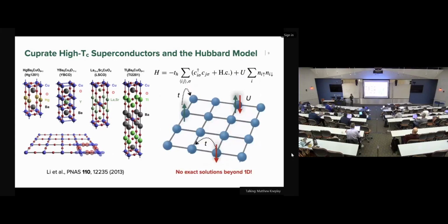The simplest model believed to capture all the key ingredients is the so-called Hubbard model, for this copper-oxygen plane. The corresponding Hamiltonian operator basically describes the energy. The first term is the hopping of electrons. For example, c_{jσ} is an electron annihilation operator, which kills an electron at lattice site j with spin σ, which can be up or down. And c†_{iσ} is an electron creation operator, where I create an electron at site i with spin σ. The Hamiltonian needs the Hermitian conjugate, so you have to have this term.